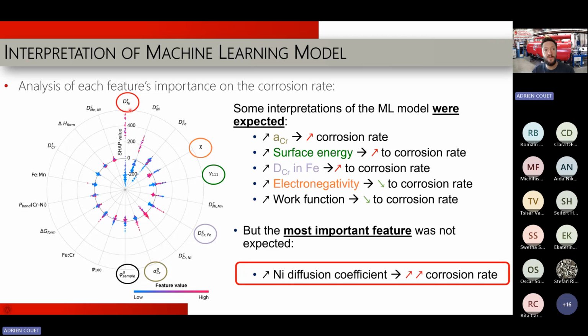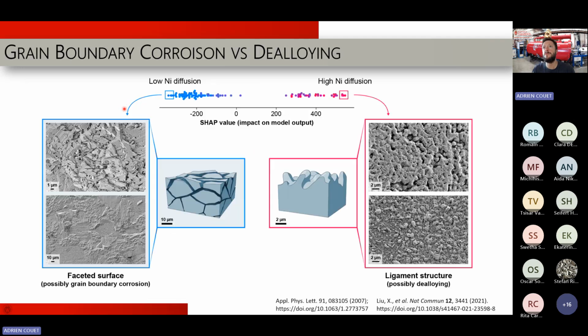But what's very interesting is that the most important feature of all is this diffusion of nickel that we didn't expect. Really, we didn't expect that if you increase the diffusion coefficient of nickel, then the corrosion rate will increase, because nickel is supposed to be noble. So we're trying to understand this. We think that there is a relation to surface diffusion, for instance.